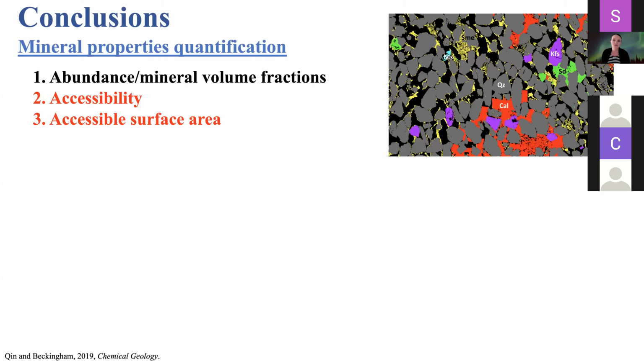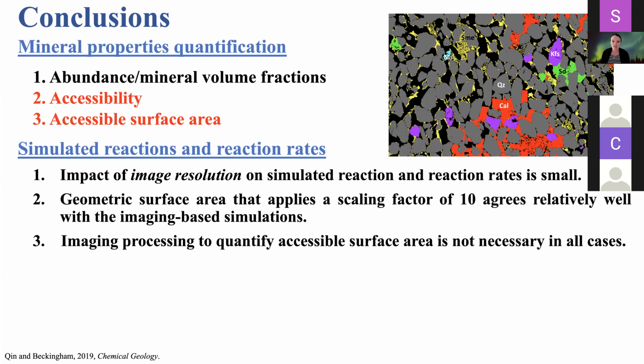So in terms of the properties you're going to get from the images to build your reactive transport simulation, there was little variation in the mineral volume fractions. We saw some variation in accessibility and accessible surface area. But even though we had these variations, they were within one order of magnitude, and they had really little impact on the simulated mineral reactions and reaction rates. We also saw in this case that the geometric surface area that applied a scaling factor of 10 actually agreed really well with the image-based simulations.